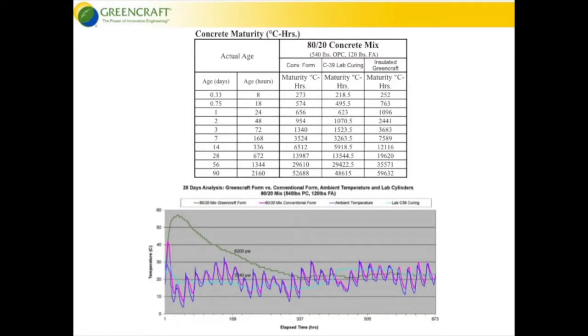So we look at maturity, Celsius hours, in these three instances: conventional form, lab curing, and the insulated form. Everybody starts at the same line, and then you start seeing the segregation. At 24 hours, we almost have twice as many Celsius hours packed in the insulated form. At 3 days, we're almost three times as much. At 7 days, you're more than double. As time goes on, the difference gets narrower.